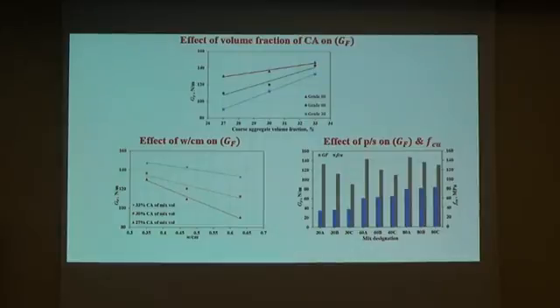Regarding the effect of water to cementitious material on GF, as expected, GF decreases as the water to binder ratio increases. And the third parameter in this study is the effect of paste to solid ratio on GF. It can be seen that there is a slight increase in the compressive strength when the paste to solid ratio increases, but there is a noticeable decrease in GF when the paste to solid ratio is increased.